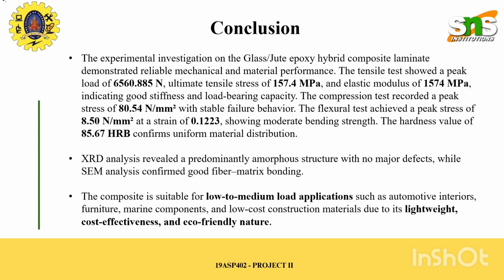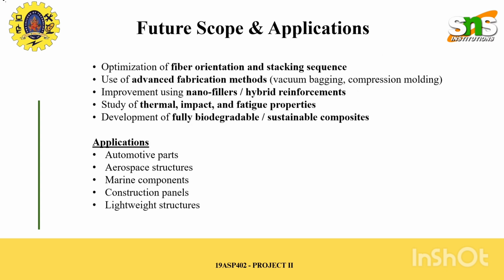In conclusion, the experimental investigation demonstrates that the glass and jute fiber reinforced epoxy composite has reliable mechanical and structural performance. The tensile, compression, and flexural results indicate good strength and stiffness, while hardness values confirm material consistency. The composite is suitable for low to medium load applications such as automotive interiors, furniture, marine components, and construction materials.